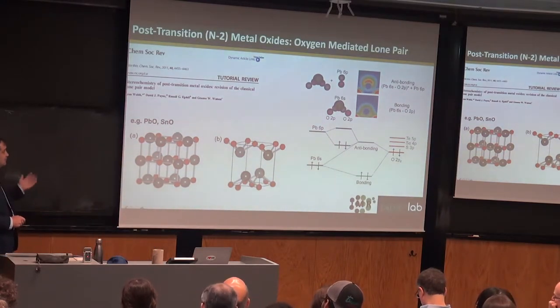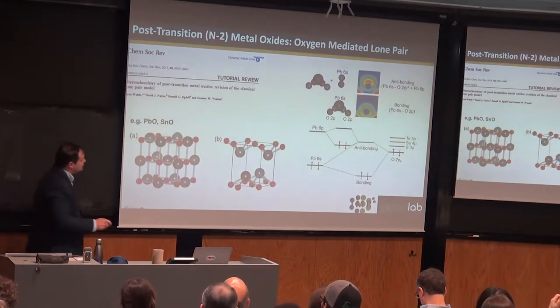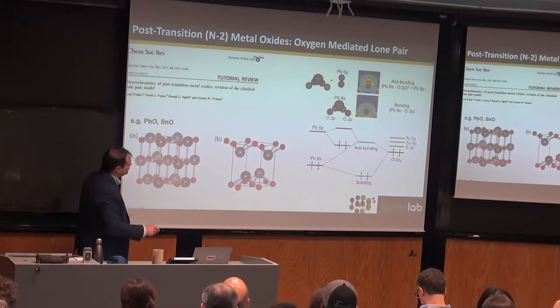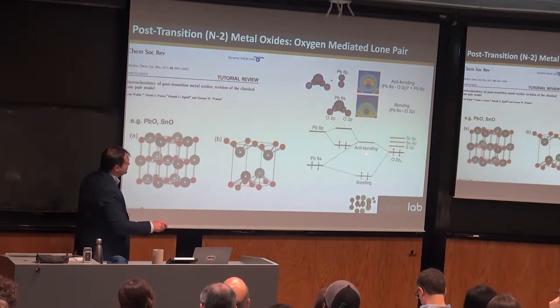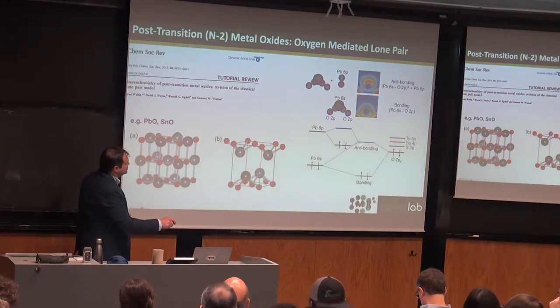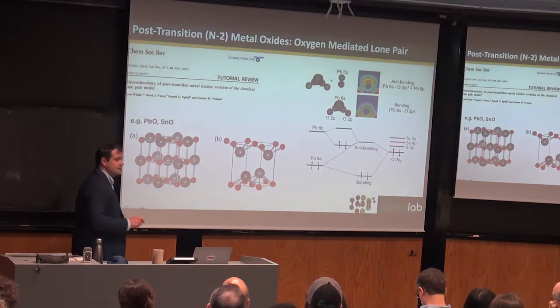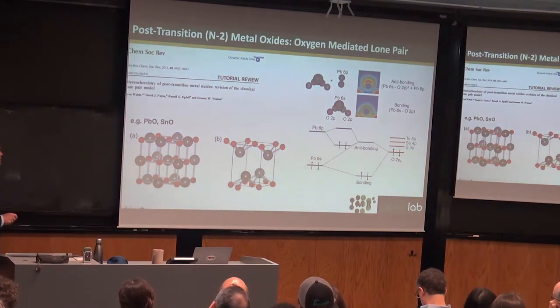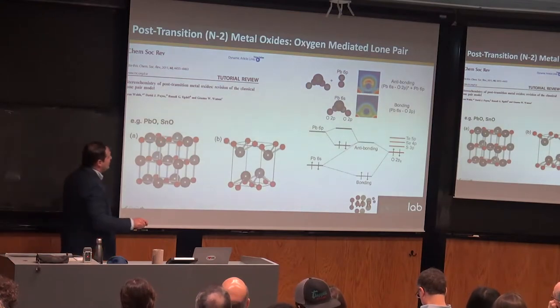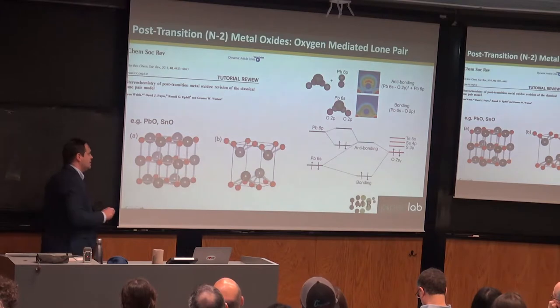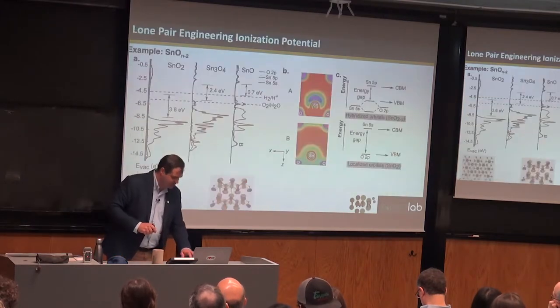And the X-ray spectroscopy combined with density functional theory showed that the origin was this hybridization of the oxygen 2p orbital, which facilitated bonding and antibonding states. And these antibonding states could then hybridize. So this would be mixed S and P orbital character mixing with the metal SP to form your lone pair states. So the key with this is we have this model of how we can play with these lone pair states. What can we do as a result?